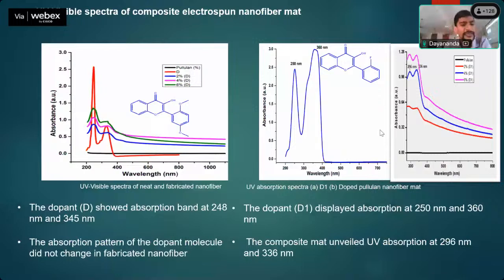The absorption pattern of the dopant molecule did not change in the fabricated mat. After incorporating in the nanofiber mat, the UV band did not change. That is because in this dopant, there was not much interaction between the dopant and the polymer. But in case of the fluorine containing dopant, one could see the first band was shifted.